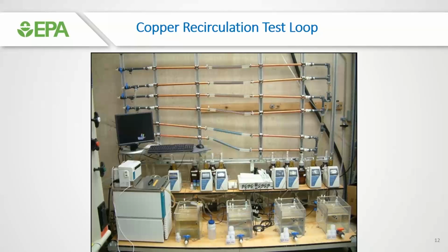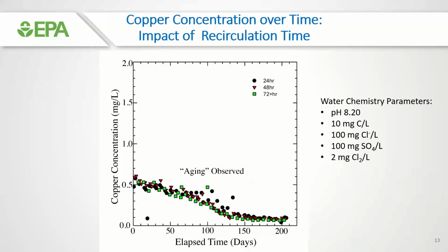Another approach is simply doing the precipitation experiments that I mentioned. Just add copper to your existing water chemistry, filter the particles out that form, and look at the soluble fraction left, and that gives you a pretty good indicator of the worst case copper levels that you might see in a system. You could add orthophosphate to those jar tests, as we'll call them, and precipitate copper and get a sense for what dose of phosphate you need to get below the action level of 1.3 as well. In these experiments, we recirculated water around copper loops, and I'm not going to go into too many details to save some time here, but this illustrates the aging effect.